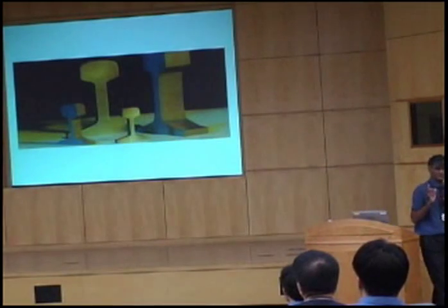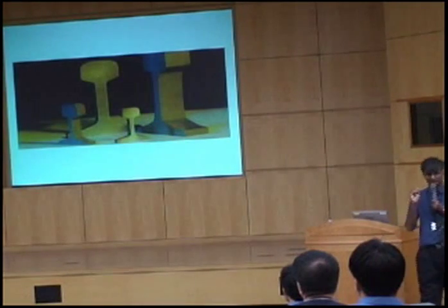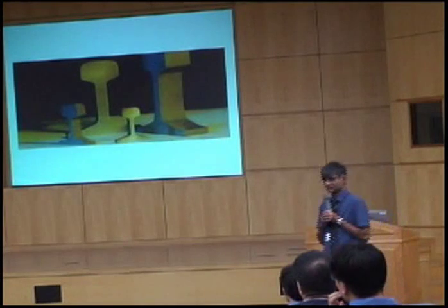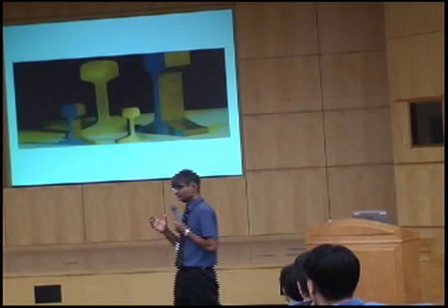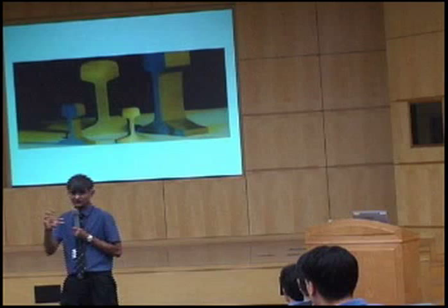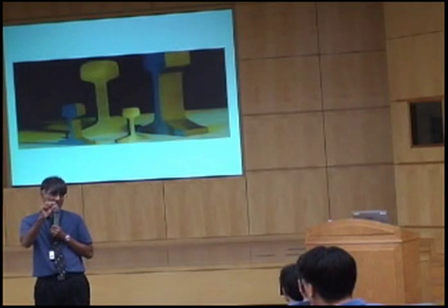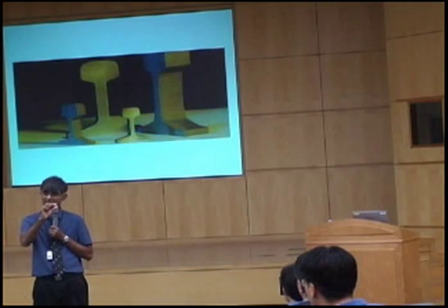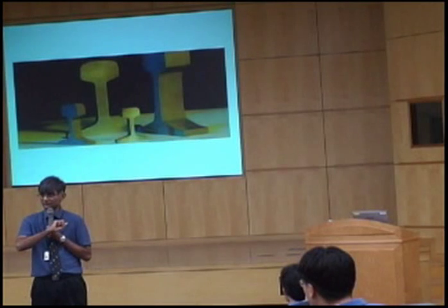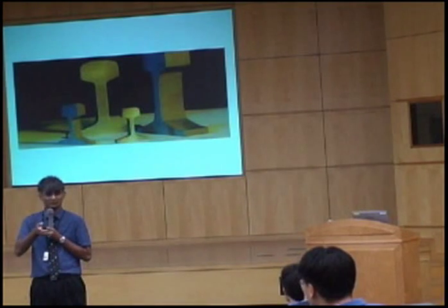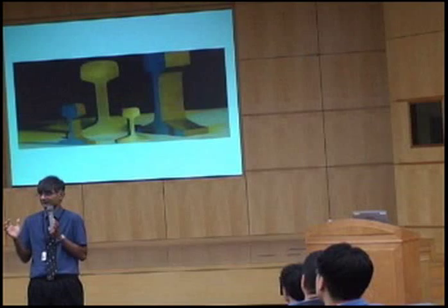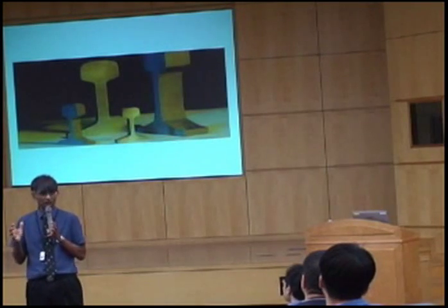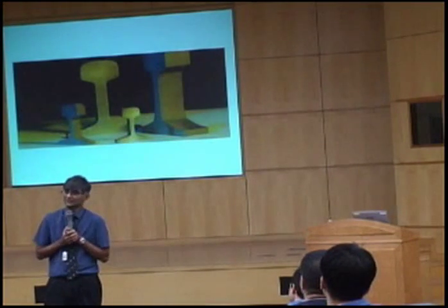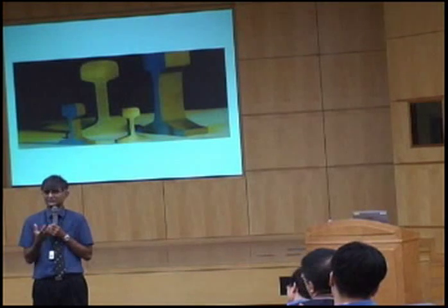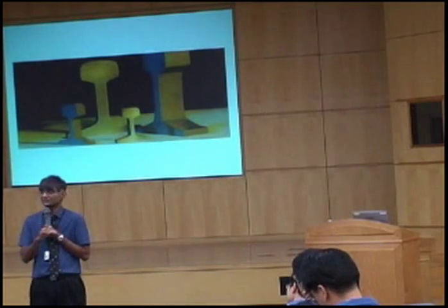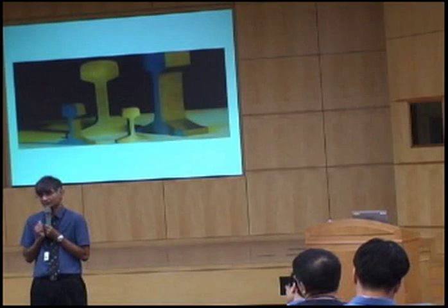We use this concept to design a completely novel microstructure for railway steels. Yesterday I explained to you that the toughness of pearlite doesn't improve when you make the distance between cementite and ferrite smaller. The strength improves and the wear resistance improves, but the toughness doesn't, because the crystallographic size of pearlite is the colony size. Right? So we have made many rail steels which are harder and are wear resistant, but they are not tough.